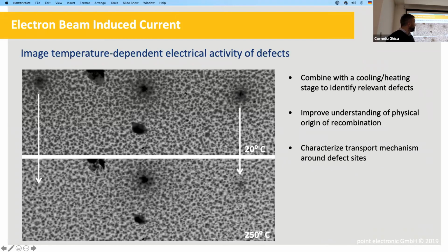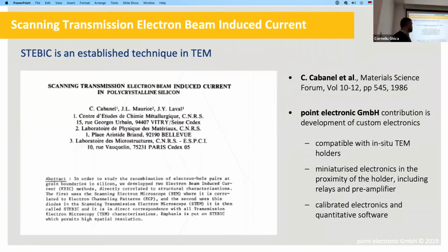And we know these are the defects, we can see them, and this is at 20 degrees, and if you go to 250 degrees, we see the contrast, so the amount of recombination of these defects is changing. And that is giving us information about the level of these defects, and then we can start to associate them with what impurities or what could be the origin of that recombination.